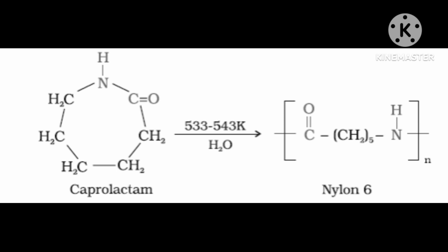Then it will be a straight chain. One end will be NH and the other end will be CO, because the C-N bond is breaking. Here the temperature you are using is high, 533 to 543 Kelvin in the presence of H2O. Then only this bond is breaking, nothing else is happening.